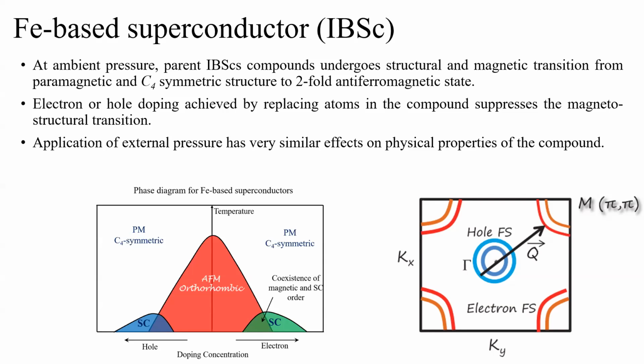The interesting part in this compound is that there is a part of the phase diagram where both the superconducting phase and the antiferromagnetic phase coexist. People don't know why these phases coexist in these compounds, and we're looking at this. Because of this coexistence, people think that probably the nematicity in the compound or the spin fluctuation is responsible for the superconducting phase in the compounds.